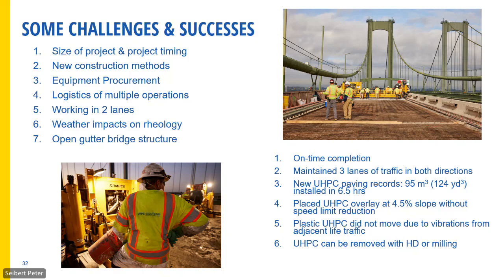Some successes, we completed the work on time with a very high quality. We maintained 3 lanes of traffic in both directions at all times, other than when we put the barrier out, of course. We did paving records of 124 cubic yards in 6.5 hours, very smooth operations. Really got our guys trained and everybody kind of bought into the overall scheme between the carpenters and the demolition teams and the guys finishing concrete. It really worked out great. Placing the overlay with the heavy slope and no speed limit reductions, no issues due to vibrations, which just a couple of years earlier wouldn't have been possible.